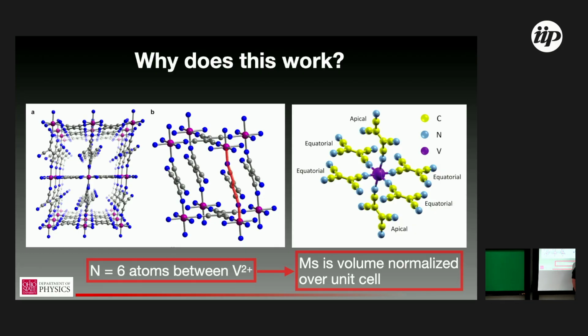It requires a little bit of thinking about what M sub S actually is. The way it's commonly defined in these heuristics from the previous slide is its volume normalized spin density over the volume of the unit cell. So it's intrinsic. It's not volume normalized in that sense, varying sample to sample, but it does depend on the size of the unit cell, and VTCNE crystal structure is incredibly porous. I'll say more about that at the very end of my talk.